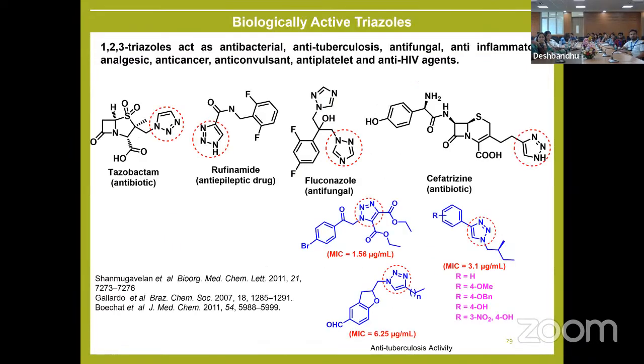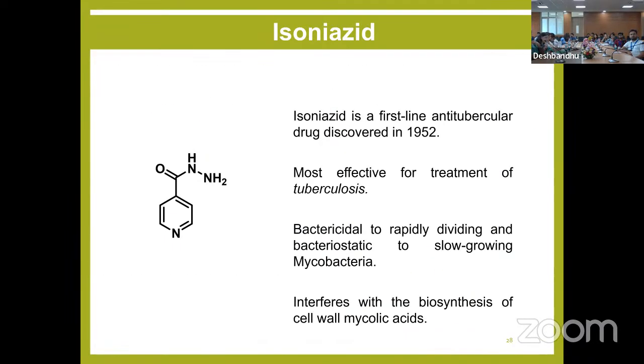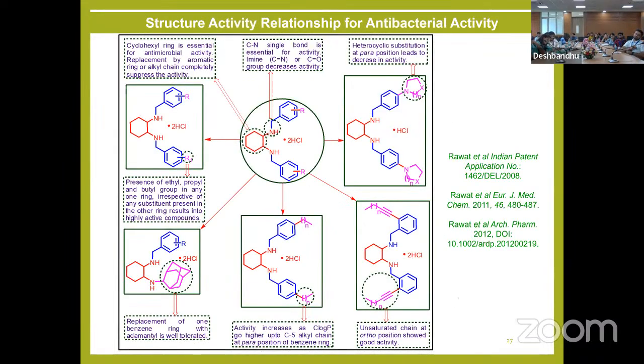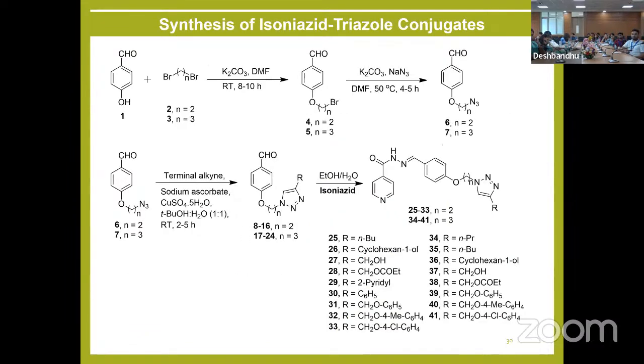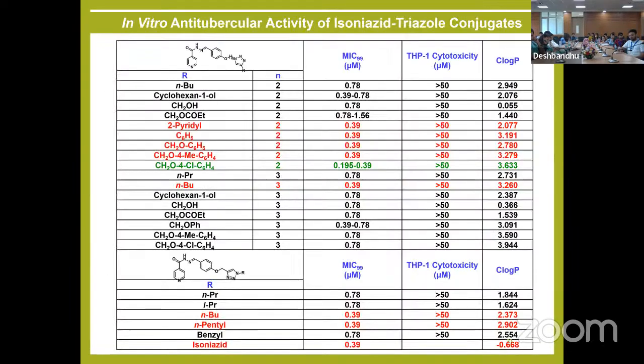Then further, we worked on isoniazid, which is used as a first-line anti-tubercular drug. We synthesized various derivatives of this compound. We linked this compound with a triazole moiety, and these compounds were also tested for their activity against Mycobacterium tuberculosis. And here isoniazid, the drug which is used for tuberculosis, has 0.39 micromolar activity. One of our compounds shows activity equal to isoniazid.